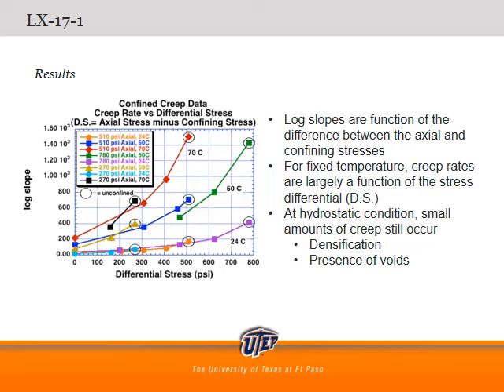While temperature still has an effect, the creep rates are largely a function of the stress differential, which is the difference between the axial stress and the confining stress. At hydrostatic conditions, where the axial stress and the confining stress are equal, small amounts of creep still occur, and this is due to densification of the material as well as presence of voids in the material.